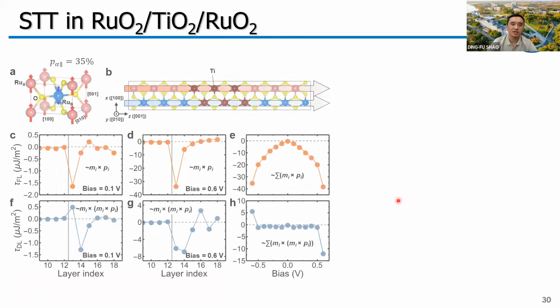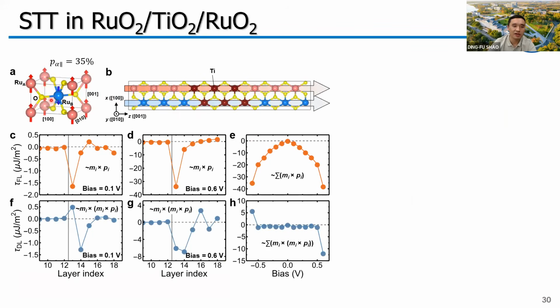So in order to demonstrate this, I first calculate the spin polarization. I calculated ruthenium oxide and found that ruthenium oxide has very strong Néel spin currents, where the spin polarization is about 35%. This value is comparable to that of spin currents in the conventional ferromagnetic metals iron, cobalt, and nickel. And then we use ruthenium oxide as the electrode and titanium oxide as the barrier to build such a tunnel junction and calculate the STT in the right electrode generated by the tunneling of the Néel spin current. We found that the STT is large at the interface, then becomes small,